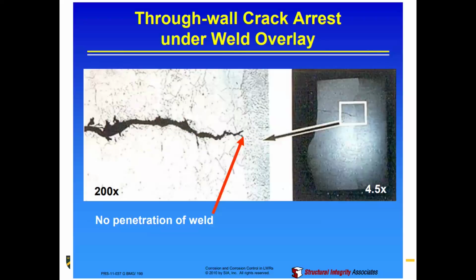Okay, so through wall crack arrest under weld overlay. I really like this image for showing how effective this can be. If you've chosen the right material that's going to be really resistant to this intergranular stress corrosion cracking, you can see that in this case, the 304 steel or whatever steel is experiencing IGSCC has completely stopped cracking at the area of the weld overlay. So very effective.